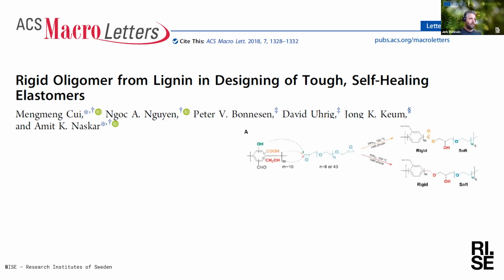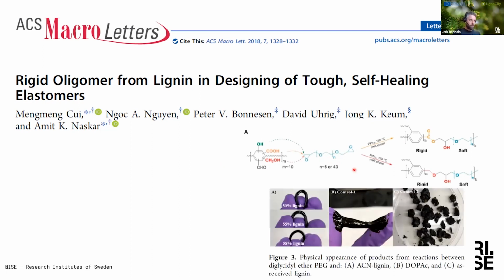What they did was they took lignin, some part of the lignin, one should say, and reacted it. So this here represents the lignin with its functional group pointing out, and it can react with this cross-linker. It's polyethylene glycol diglycidyl ether, a tricky word. It's quite tricky in its abbreviated form as well when it's called PEG, but there you go. They reacted with this and get an elastomer, an elastic material, which looks like this.